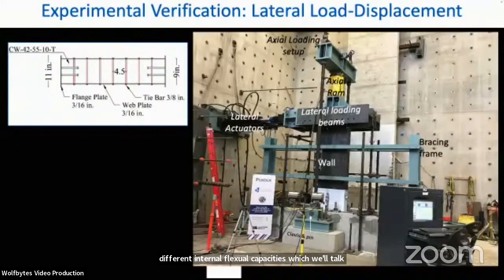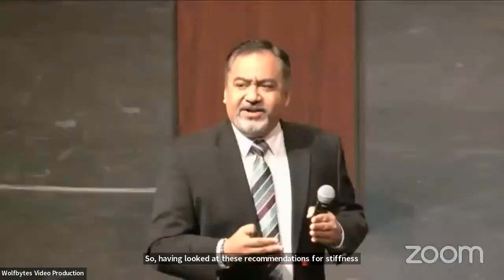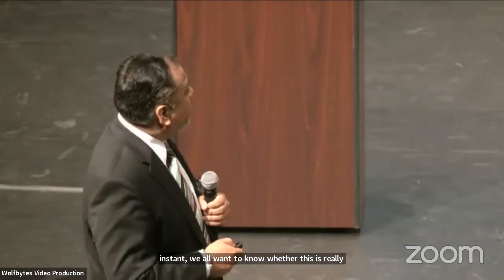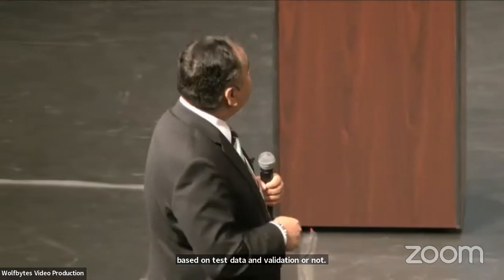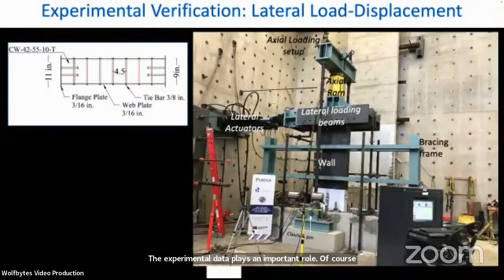So having looked at these recommendations for stiffness and strength, we all want to know whether this is really based on test data and validation or not. The experimental data plays an important role, of course, in all of this research. So we developed some specimens that were about 1/3 scale representations of the full-scale steel plate composite walls, and we tested them in our laboratory under axial compression and cyclic lateral loading using actuators.